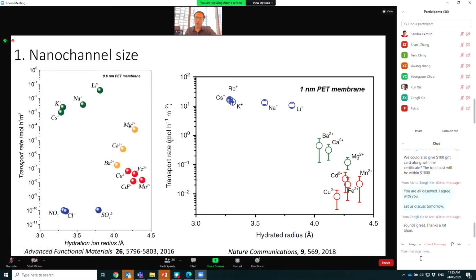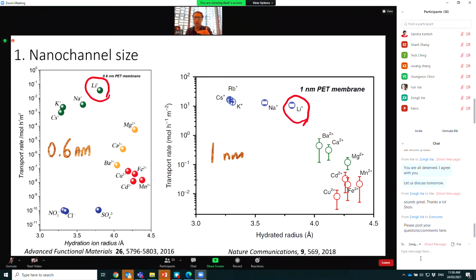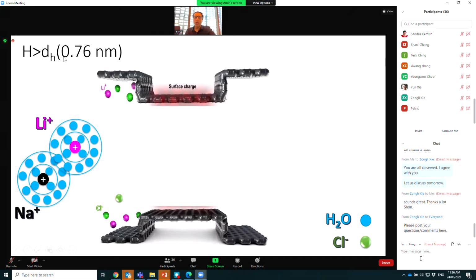So let's go through these parameters one by one and see how we could draw universal principles, which is very difficult currently because we don't have enough information in the literature. But for example, for nanochannel size, when we have a nanochannel diameter of somewhere around 0.6 nanometer, the membrane showed lithium selectivity. When they increased the size to above 1 nanometer, the membrane lost its selectivity. So when we talk solely about the channel size or the pore size, and ignore the contribution of other chemistry and functional groups, the size matters a lot in the sense that it has to be below the hydration diameter of